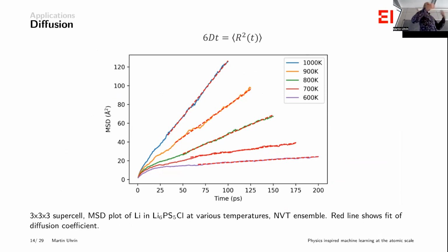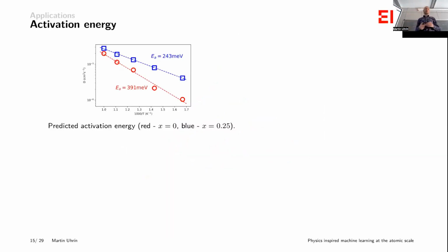So what GE did was, of course, we need to make sure that the unit cell we're using is large enough to capture the conductivities that we want. He did some nice convergence on this, and then we can look at how the lithium is diffusing as a function of temperature. And from the gradient of these lines of diffusion, we can calculate the conductivity and also the activation energy of a typical hopping for lithium, which is particularly attractive because that's something that we can readily compare with experiment.